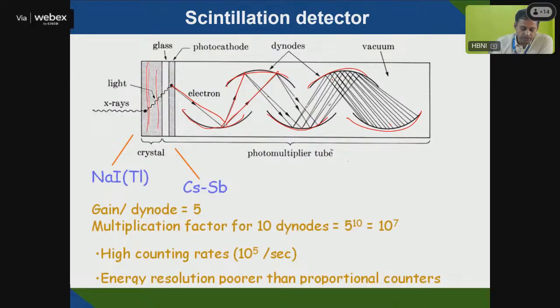So using this type of sodium iodide thallium detector, even a low intensity X-ray can be amplified, and the photomultiplier tube will finally give you the energy resolution poorer than a proportional counter, and you'll get all those diffraction patterns.